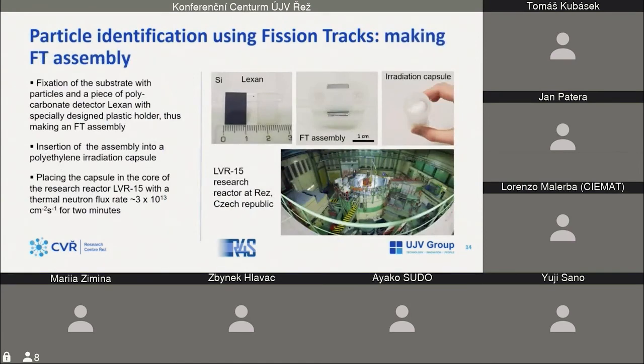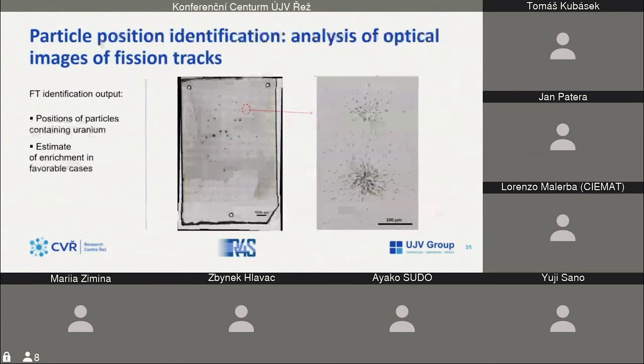We have developed our own innovative procedure. It involves creating a so-called fission track assembly, which is a sandwich of silicon substrate, particles and Lexan, held together by plastic brackets, which you can see on the right-hand side. This fission track assembly is inserted into an irradiation capsule and exposed to neutrons in our LVR-15 nuclear reactor. The dose which we use is about 10^15 neutrons per square centimeter. Here is the outcome of this experimental exercise.